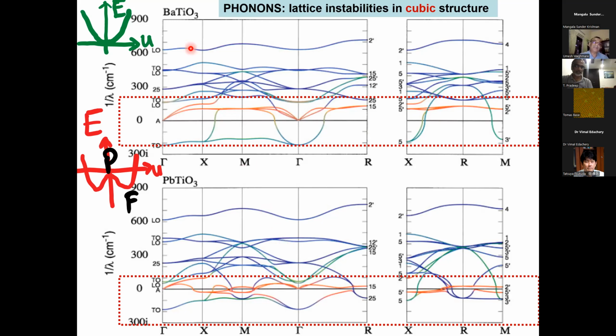I remind you that these phonons in blue are high energy phonons, and the energy well associated with off-centering of these vibrations or atomic displacements is a single energy well. And that type of energy well you can integrate out from your thermodynamic statistical mechanics analytically. On the other hand, the phonons in these red dash boxes are unstable. These are the lowest energy phonons. And for them, the energy well associated with atomic off-centering is a double well function that I introduced to you earlier. And these we cannot analytically integrate out of the statistical mechanics partition function.